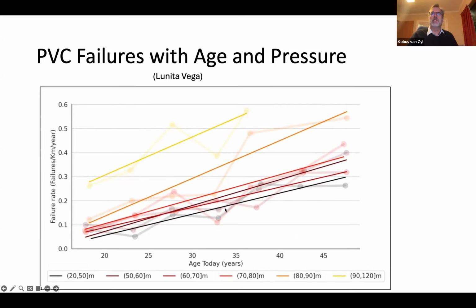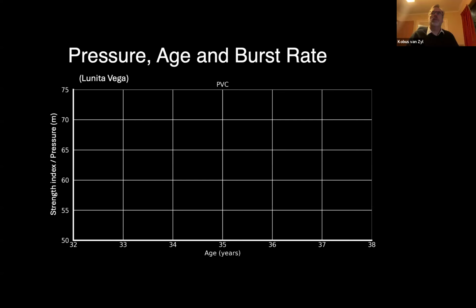So what the data shows is that the lower pressure pipes have the lowest slope there. And as you increase the pressure, the slope actually increases. That's the general trend, that the failure rate increases, but also the slope seems to increase a little bit. And so we then said, okay, we can model this process.